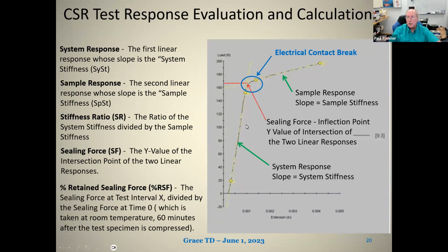One thing you get out of this is if you take the ratio of the system stiffness and the sample stiffness, which are the slopes of the two, you get what's known as a stiffness ratio. When you do CSR testing, you want to have a stiffness ratio that's greater than 5. If you have a stiffness ratio that's between 2 and 5, you need to note that. Depending on how linear your response is and the quality of your inflection region, you may be able to say that it's good and you still have a valid value. If the stiffness ratio is less than 2, you can't really say with any certainty that those values are correct.